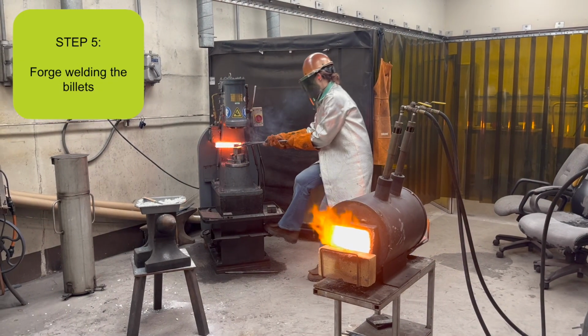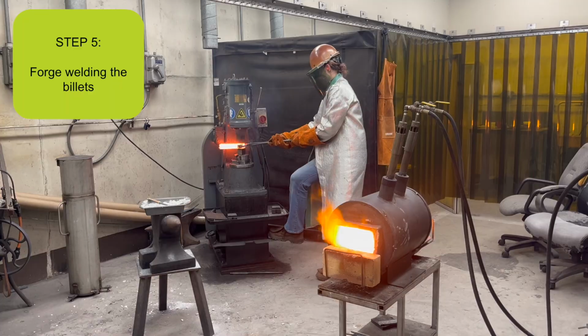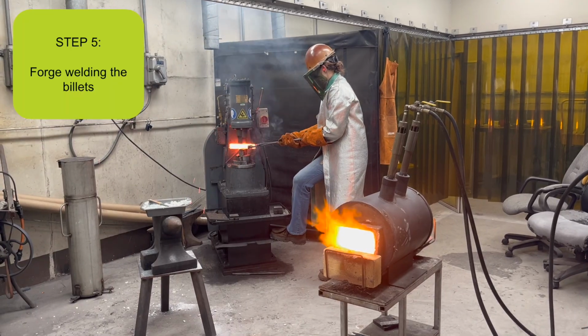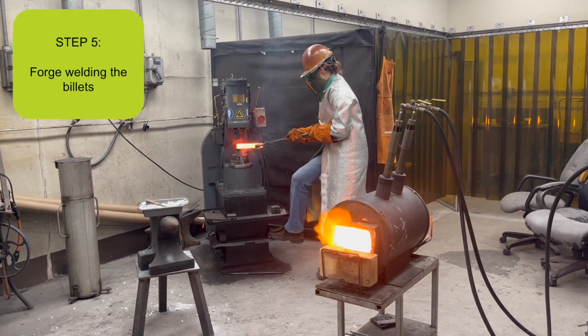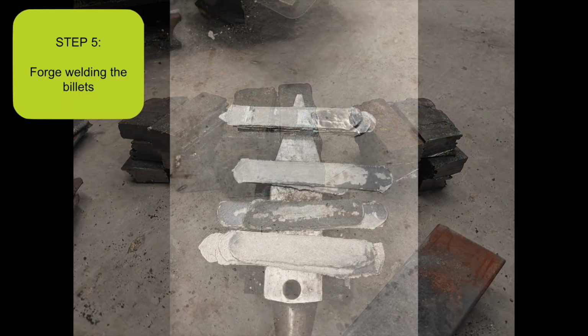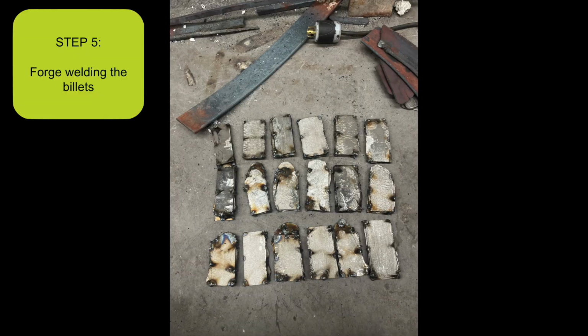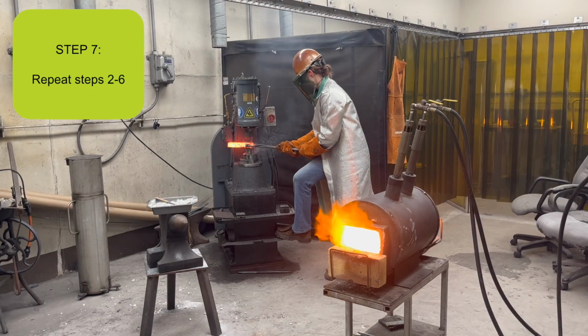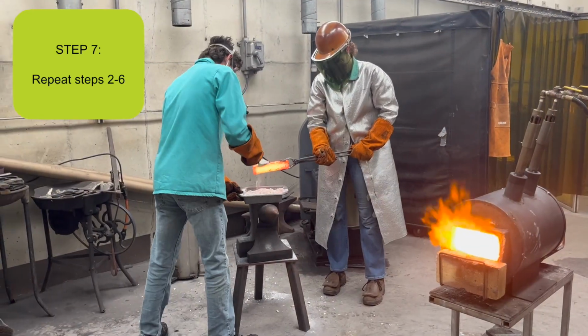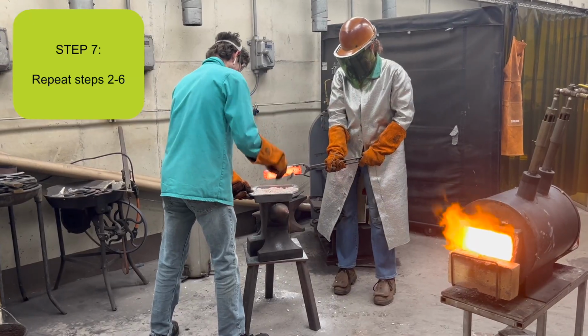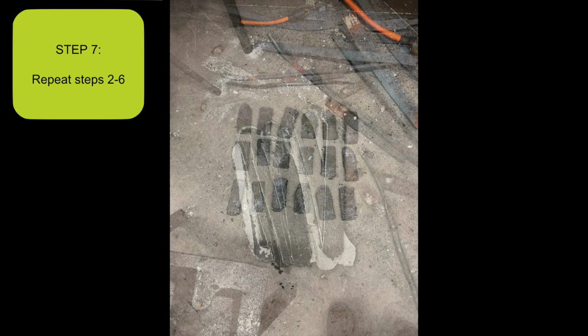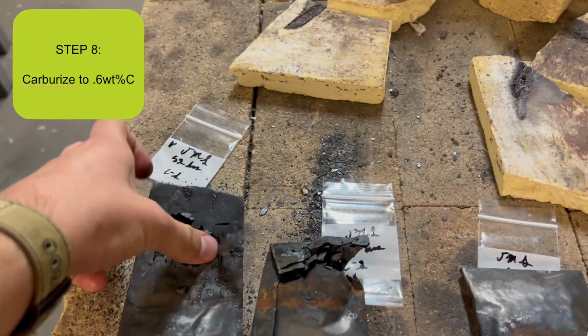They were then forge welded together using borax as a fluxing agent and cooled before being wrapped in steel foil for the process of hot rolling and recombining to begin again. This step was repeated to attempt to remove more of the impurities from the original manufacturing of the metal through the mechanical and chemical process of forging with a fluxing agent. After the second round of rolling was complete, the process of carburization began.